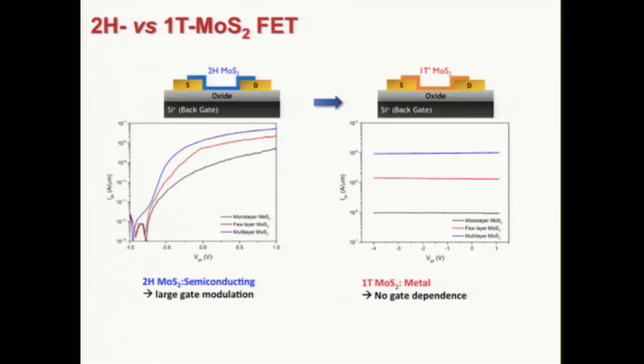So here we can compare metallic and semiconductor MoS2 FET transistor. By the way, the semiconducting one is labeled 2H, and the metallic one is labeled 1T or 1T prime. As expected, the 2H one has a very large on-off ratio. It's a semiconductor channel. But after the phase transition, when we have a metallic channel, the current is constant because we cannot deplete it. There's no band gap.